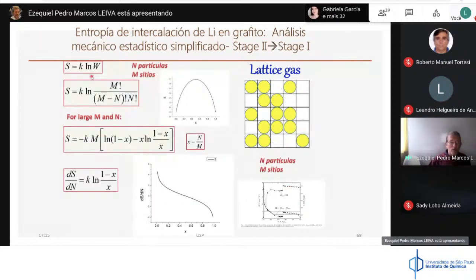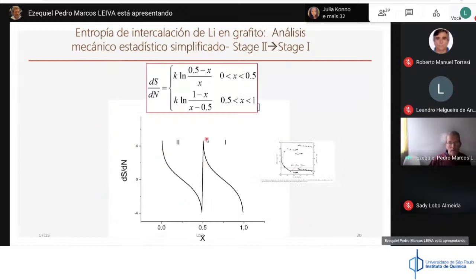You know that the entropy is proportional to the degeneracy of the system. If you put a lattice gas on a model, you put N particles on M sites, you will see that the entropy goes to the maximum, because when you fill 1/2 of the sites, you have the maximum entropy. As you take the derivative of this curve, you have this partial molar entropy behavior, which looks something like experiment, but you don't have a step like this here. If you consider the addition of 2 systems, that is the filling of 2 lattices, you expect something like this. This is very roughly stated, but you fill 1 layer and you fill another layer, and you would expect to find a huge step.